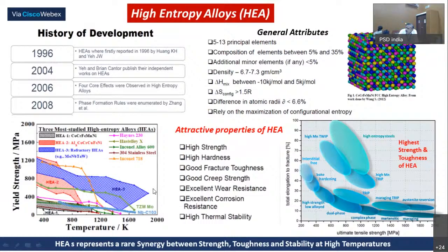Okay. Now, on the left side of the diagram here, you see temperature versus yield strength. One of the most dominant alloys starts dropping its strength as you cross 1000 degrees centigrade, that is close to 1200 K. But high entropy alloys, particularly refractory based BCC metallic alloys, retain their strength up to 1600 to 1800 K, that is 1400 degrees centigrade.